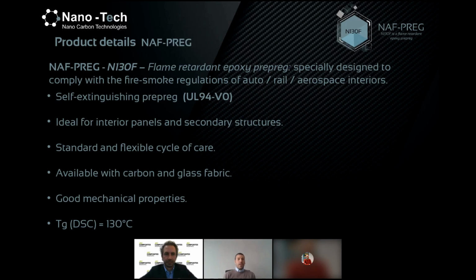Then we developed this composite, the NAF-PREG NI30F, a flame retardant epoxy prepreg, specially designed to comply with fire and smoke regulations, so FAR and UL 94. It's ideal for panels and secondary structures. It's already under testing for interiors in aerospace. It's available in carbon version and also glass fabric version, and it has very good mechanical properties.